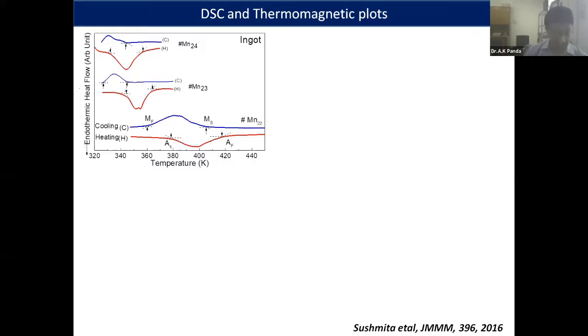Here the red one is the austenitic cycle, where it is the end of the martensite, start of the austenite, and the austenite finish. Because it is a depleting martensite, and it is an enhancing austenite state. So this is how you get the two cycles. And what you find is that with increasing manganese content, it shifts to the left.